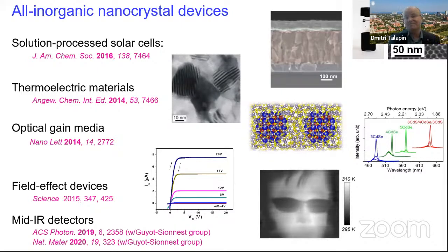And my lab spent quite a lot of time working on different all-inorganic nanocrystal devices, implementing ideas that we developed for surface engineering to achieve good electrical conductivity. And within this domain, nanocrystals can be used for solution processed solar cells, thermoelectric materials, optical gain media, field effect devices, and infrared detectors.